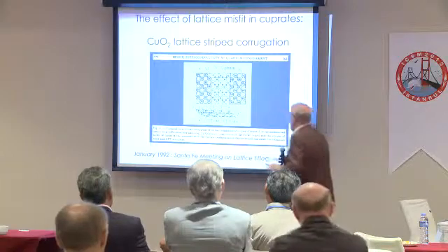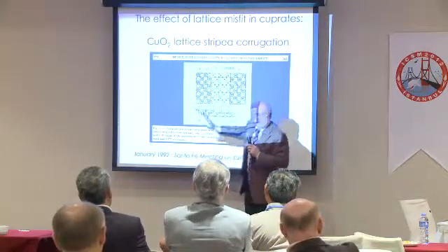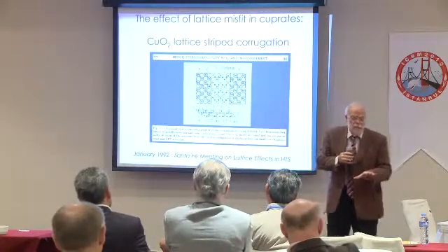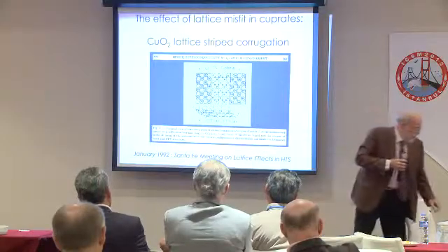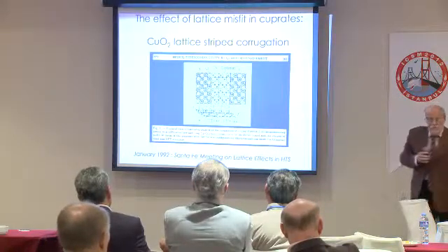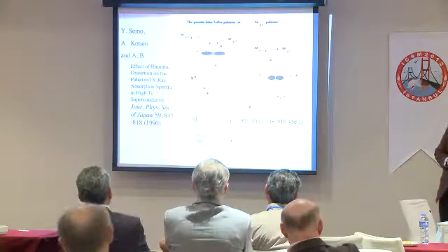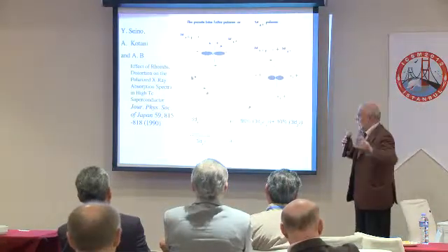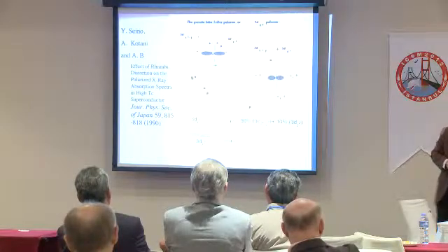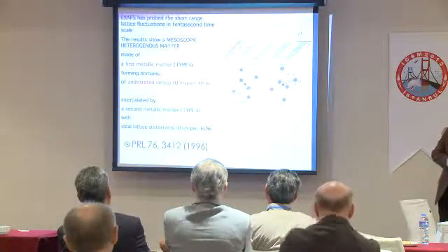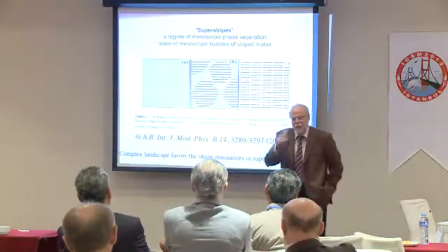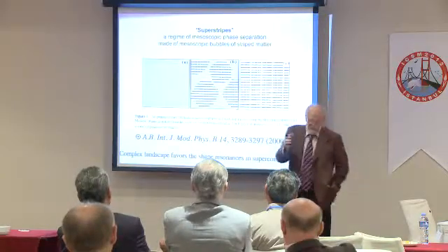Two different metals. These are two metals. There is no antiferromagnetic spin. There are two metals, one distorted, one undistorted. So it's a texture, a material texture. And this is true for all materials where compression is above the critical value for high Tc. So the Jahn-Teller polaron produced this kind of phase separation between distorted lattice and undistorted lattice. So this was achieved by EXAFS and by many other techniques, by Mössbauer and Kushalev and Shengelaya.